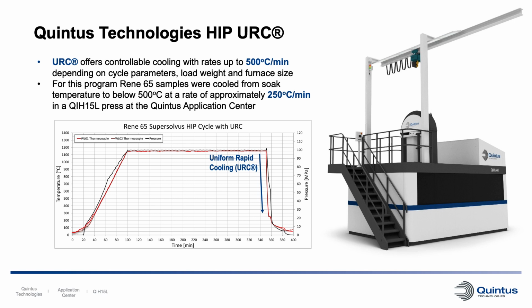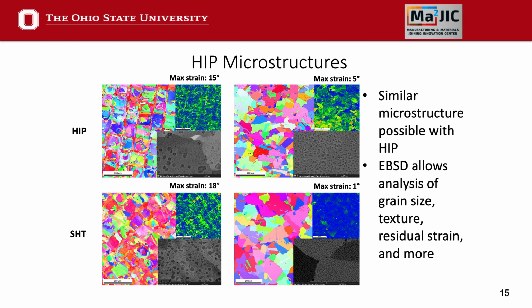Yeah, so the ability for the Quintus machines to do rapid cooling is one of our big draws to this equipment. With these alloys, you get a lot of precipitate growth on cooling, so we can do rapid cooling or more controlled cooling. We have more of an ability to control the precipitation behavior, which is going to have a big impact on our mechanical behavior. So the added functionality in the HIP system gives you an extra dial to control or steer the microstructure. And understanding the process and structure relationship then allows you to dial in the desired mechanical properties.